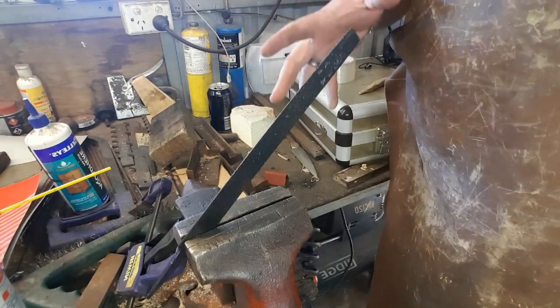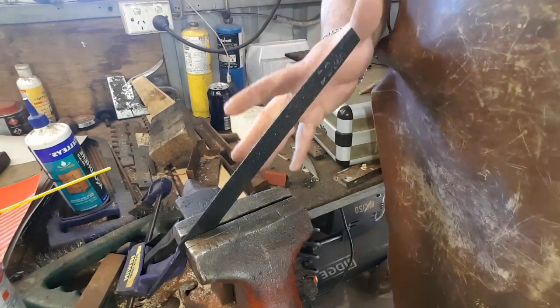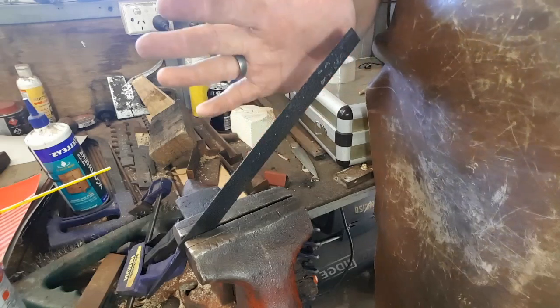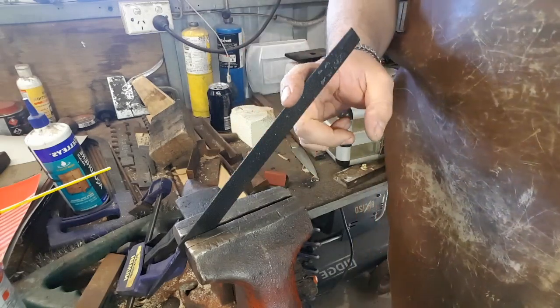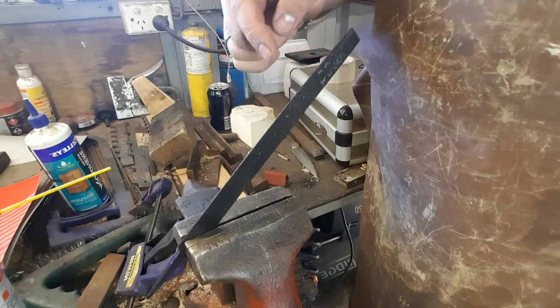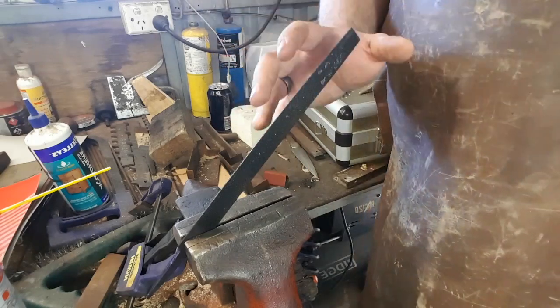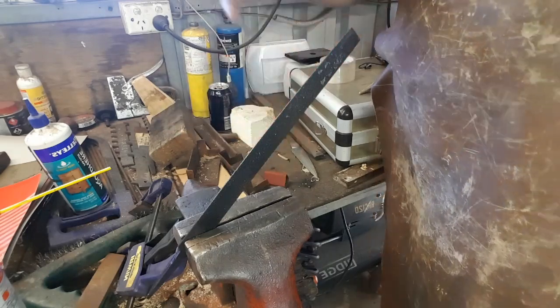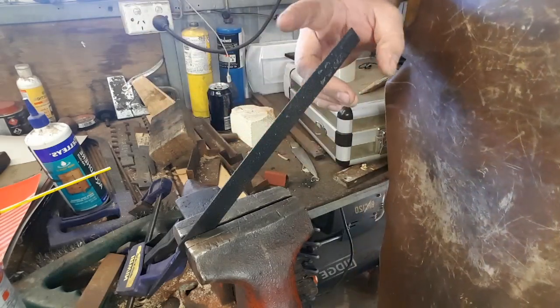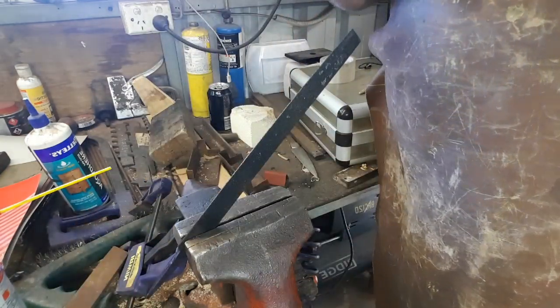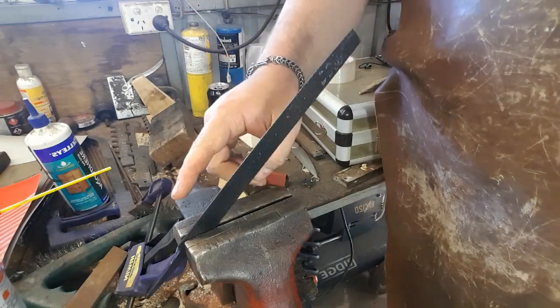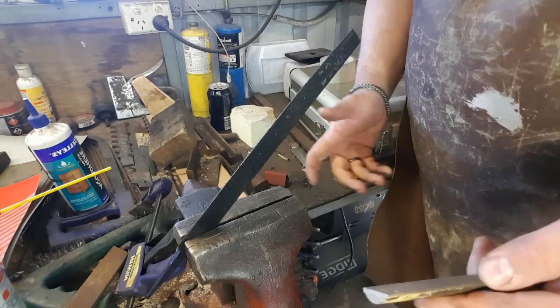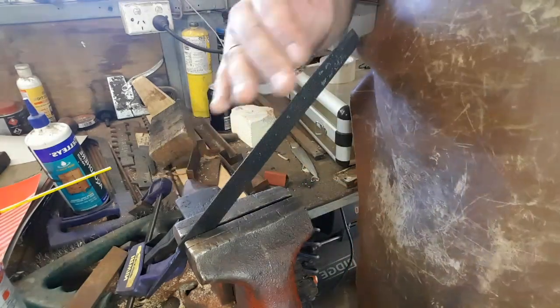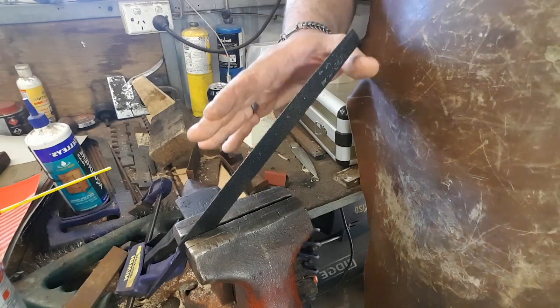Now, if you're using a charcoal forge or a gas forge or something like that, and you're not using a neutral atmosphere, so you're creating a lot of scale when you're heat treating, you may have a layer of what's called decarb or decarburization. That is where the carbon has leached out of the iron into the scale and then escaped the steel in scale. That's why I go so aggressively at it when I'm testing. Because if there is a layer of decarb, I want to cut through that decarb. If I just kind of, oh no, it's soft, I may actually only be scraping the surface of the decarburization, and I've done that a few times. And then right underneath that is the hardened steel.